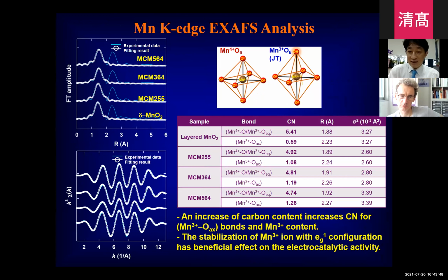Actually, for the application of manganese oxide, the stabilization of manganese 3 plus is very important because the manganese 3 plus ion gives a very efficient reaction site for the OER process. But as you know, manganese 3 plus is a Jahn-Teller active ion. So in case of manganese 3 plus oxide, we can observe such an octahedral elongation, an octahedral modification. But in case of the manganese tetravalent MnO6 octahedron, this is a regular octahedron. So in terms of bond distance, the equatorial bond distance of manganese 3 plus and oxygen is quite similar to the manganese 4 plus and oxygen bond distance. But due to the elongation of the axial, the axial manganese 3 plus oxygen bond distance is much longer than the other manganese oxygen bond distance.